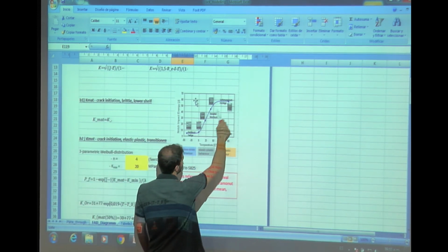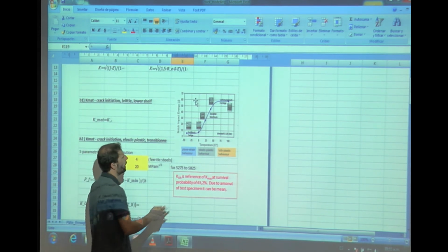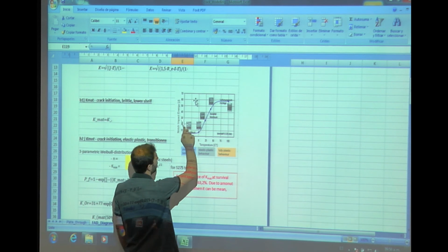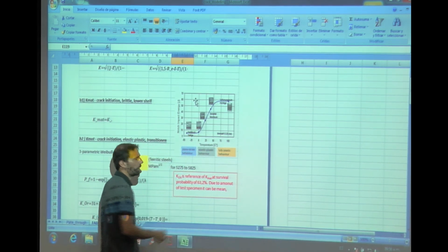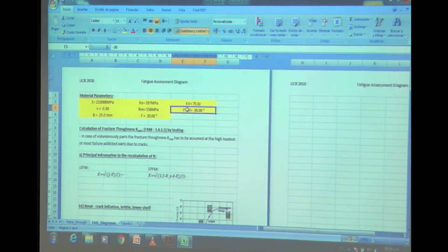And from this point to this point there is the elastic plastic behavior, and the T27 joule in this point is just describing where we have the 27 joule and the related temperature. This is something which is defined due to the material which we want to use in Europe, and so this is something which is on this level related to this.